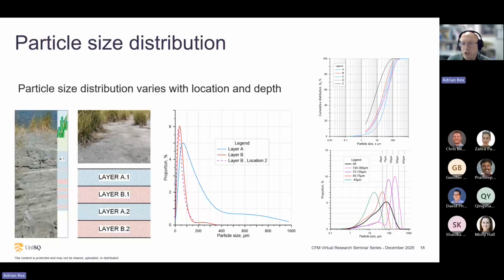Many researchers assume that one sample taken there is representative of the whole ash pond. That's not the case. And that makes the reclaiming of these ash ponds over the next couple of generations quite a challenge, because you can have some nice fine material there and some coarse material up that end. Do you blend it? Yes.